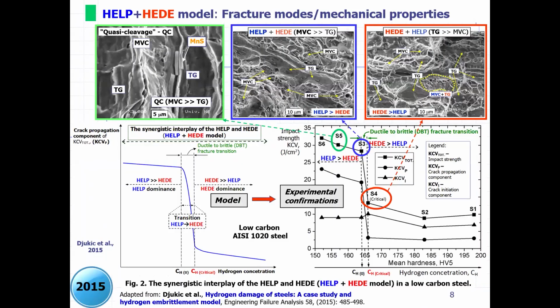Here is the original paper from 2015 in which we proposed the HELP HEDE model. We can see that we have a transition between mechanisms and the drop of mechanical property, which means particularly ductility, happens not due to hydrogen-enhanced plasticity mechanisms, but due to activation and predominance of the HEDE mechanism, the decohesion mechanism. So we have a HELP dominant regime and we have a HEDE dominant regime, and what is interesting, the fracture features of the low ductility sample and the relatively good ductility sample are very similar. So we have activity of both mechanisms manifested by microvoid coalescence, a ductile mechanism due to predominance of HELP and other plasticity-mediated mechanisms.